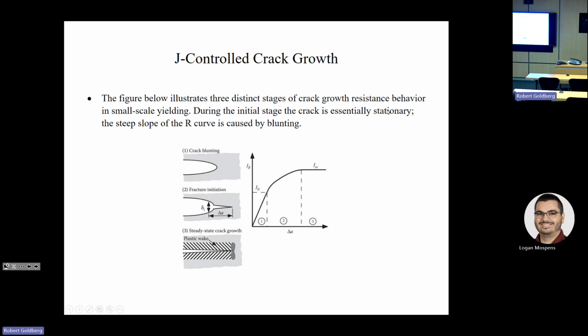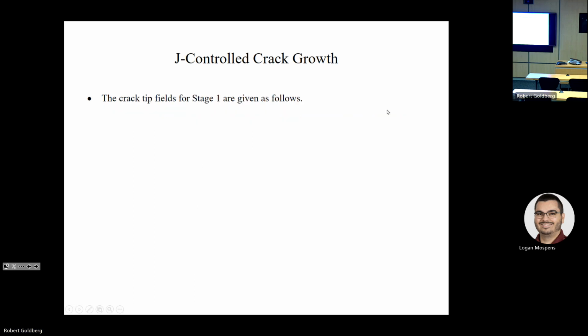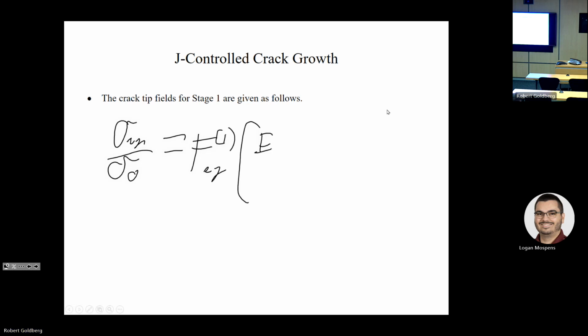So this figure illustrates the three distinct stages of the crack growth behavior in small scale yielding. Under the initial stage, the crack is essentially stationary, and the steep slope of the R curve is caused by blunting. And we can define our crack tip fields for stage one. We can say that our stress divided by our sigma naught term is equal to some function, valid for stage 1, of E prime times J divided by sigma naught squared R, and our angle theta.